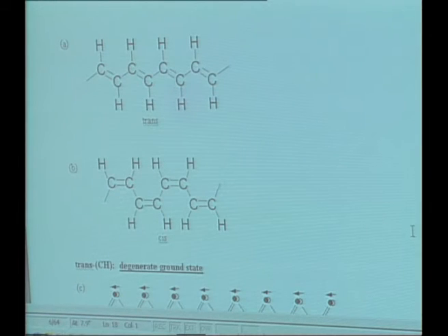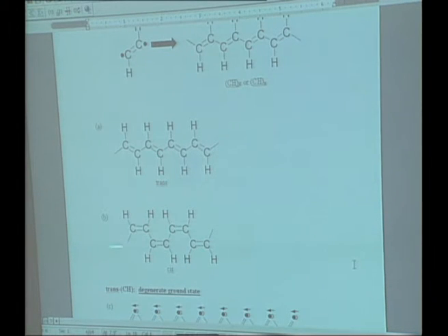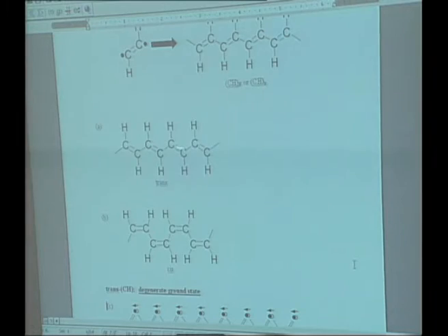It turns out, if you just look at the possibilities, one can take this structure and put it together into a polymer in either the cis polyacetylene form or the trans form. Okay? And it turns out that by using the catalysts that were, and I think still are used, Ziegler-Natta catalysts, you actually synthesize polyacetylene in this cis form, but it is not the thermodynamically stable state. The trans form has a lower energy than the cis form, and this sample that I passed around is a sample of trans polyacetylene.